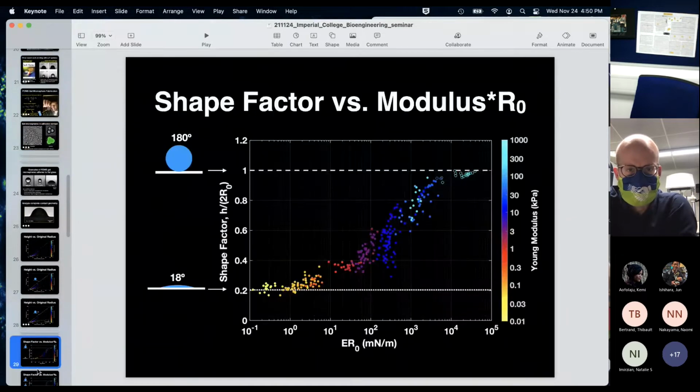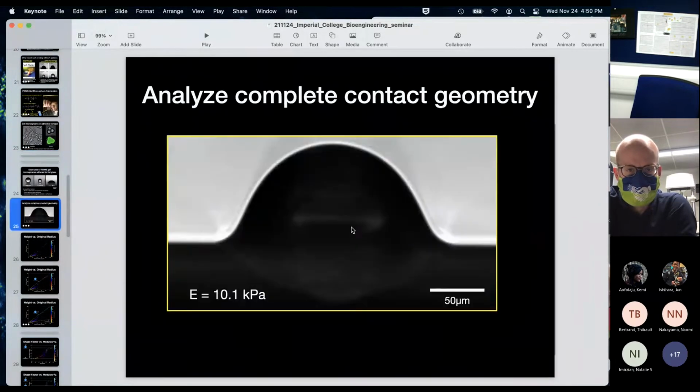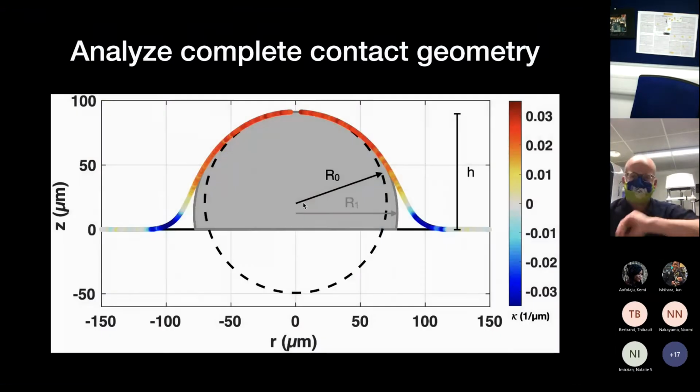In the case of the spheres, which I think is what you particularly wanted to ask about, and please interrupt me if I'm on the wrong tangent or if you want to ask further questions, we always see this foot, which indicates that there's a phase-separated fluid. Even on the really stiff ones, that was hard to see from my pictures. There's always a little bit of a fluid region. It seems to be a little more pronounced in the intermediate stiffnesses.